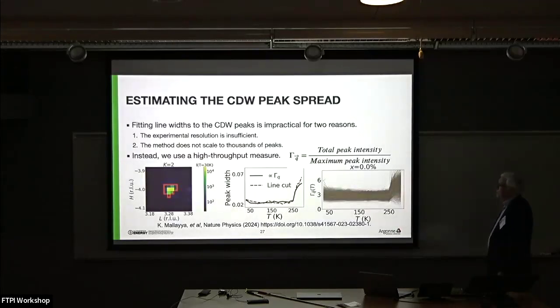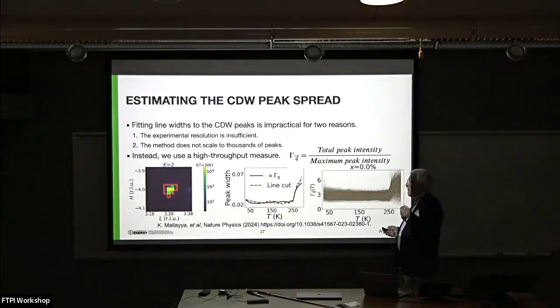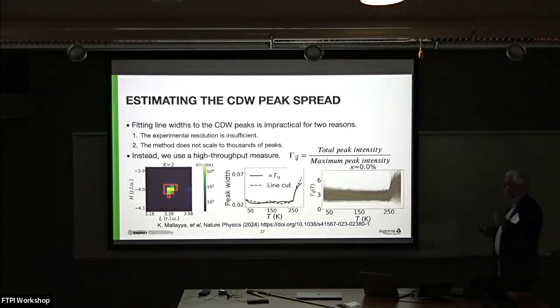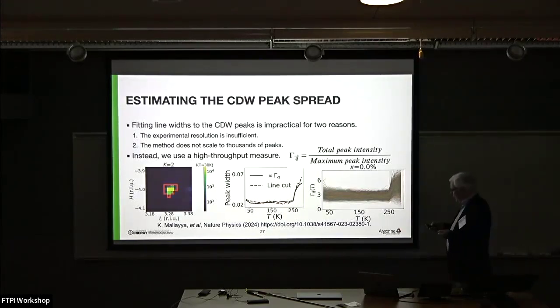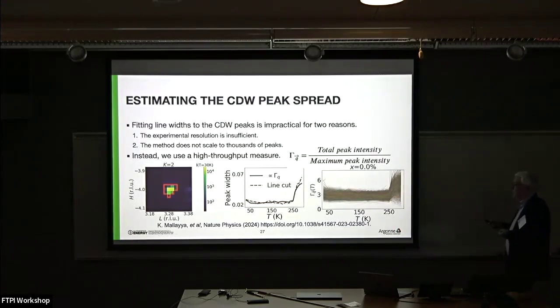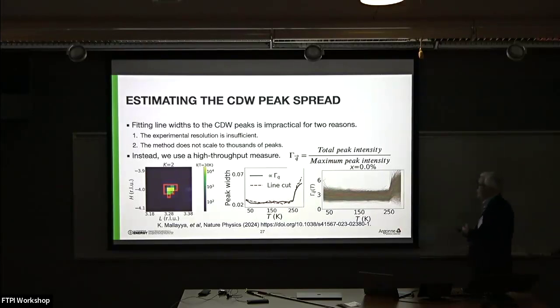So here's the idea, and they're making use of the fact that having done X-Tech, we already know where the peak intensity is. What are the pixels that contribute to the resolution limited peak? So we use those peak intensities. And they came up with this peak spread function, which I must say as an experimentalist I was initially rather skeptical of. It works remarkably well. The idea is you take the total intensity within the peak and you divide by the maximum peak intensity, and that's proportional to the line width.